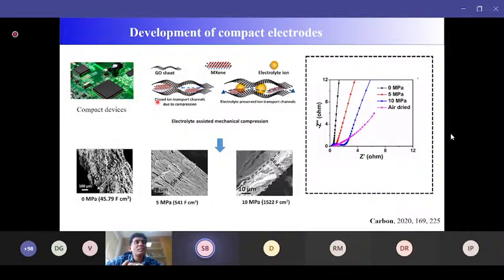And we also did another thing, because sometimes the requirement is a high volumetric capacity, when you want to use it in a compact space. The energy storage devices should be very compact, but this porous structure has a lot of water inside, so the volume is large. So we compressed them with mechanical compression. But during the compression, we first introduced some electrolyte. So whenever we did the compression, this sulfuric acid electrolyte actually keeps the sheets separated. We cannot put them completely one upon another, so there is still some space available. This is due to the electrolyte ions, and as a result of this electrolyte-protected compression, we got very good performance.